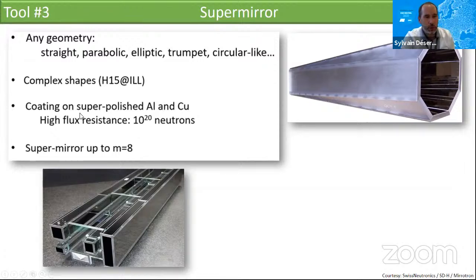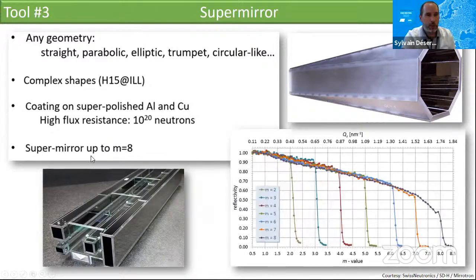So it's possible to coat on super polished aluminum and copper, which have much higher resistance to neutron flux. So this will be really useful to get these elements very close to high neutron flux. And also the suppliers are now able to coat the mirror up to m equal 8. This is a curve you can see here with a reflectivity still of about 40%.